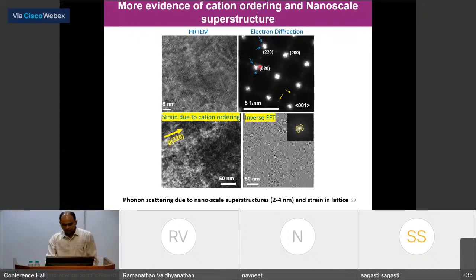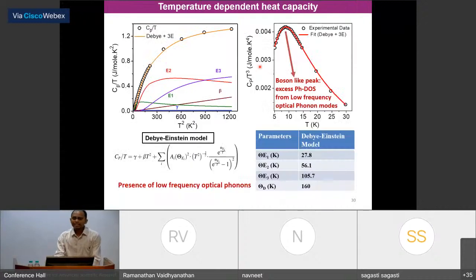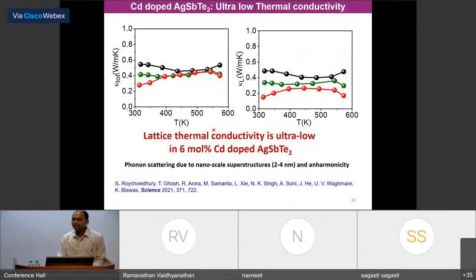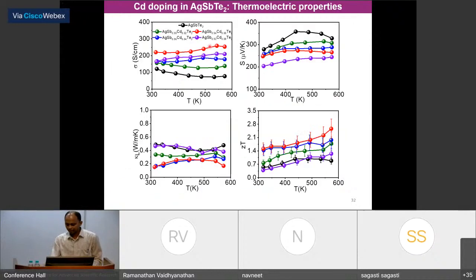So then we have done low temperature heat capacity experiment, and this low temperature heat capacity cannot be fit by the Debye model. Okay. So we have to invoke the Einstein model in addition to the Debye model, and this Einstein model is nothing but the low energy optical phonons. So in this cadmium doped AgSbTe2, the cadmium actually softens the phonon, and this is a direct proof of that, and also it scatters the phonon by creating this nanostructure domain formation. So it has two effects and decreases the thermal conductivity up to the glass limit.